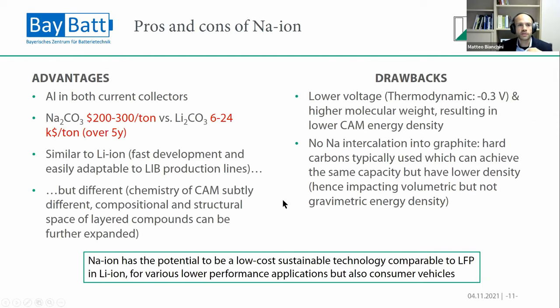So why is it so interesting to make a sodium ion cell? Well, first of all, you could use aluminum in both current collectors. So you would get rid of copper, which is already expensive. You can use sodium instead of lithium. And sodium is much cheaper, much more abundant, and doesn't have this huge price fluctuation that we've seen on lithium in the last few years.